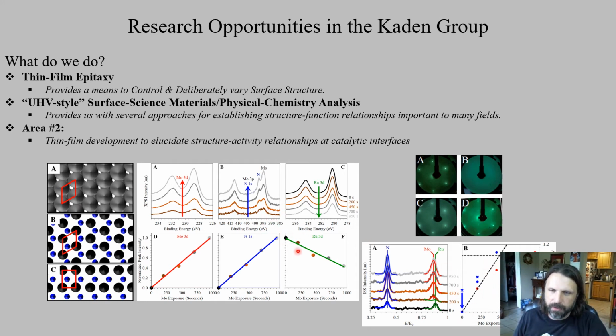This tells us about what is growing. And then finally we use the LEED like we did before, where here, like we said before, this is what the ruthenium looks like, ruthenium 0001. And then when we cover this thing with some molybdenum, initially we lose the pattern because it's a completely amorphous overlayer. And then what we do is we heat that stuff up within a nitrogen environment, and we can crystallize. And what we see is that the pattern that we crystallize to is the same as the underlying support. That's the templating effect that we use with epitaxy. So that's pretty good evidence that we made the thing we wanted to make. Okay, moving on.